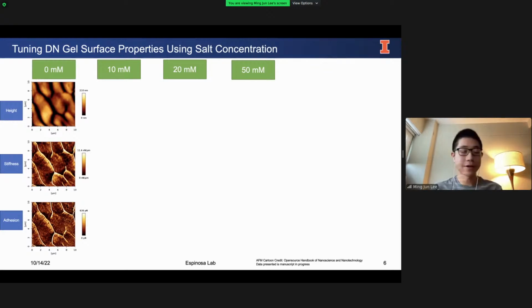I'd like to direct your attention to the first diagram on the top, the upper left. And we see a very unique microstructure for my double network hydrogel. It looks sort of like a grain structure, or even like the bubble wrap that we have in our shipping containers. The elevated orange grains, I believe, are the copolymer component, so that's the acrylamide-co-acrylic acid component, whereas the black areas that are lower in height, the valleys, I believe are the agarose network. And one reason why I believe this structure appears is that if you look at the second image, in the stiffness channel, the valley regions correspond to a higher level of stiffness. Through common knowledge in the hydrogel space, we know that agarose is the more brittle and stiffer network compared to the copolymer. So this is why I believe there are heterogeneities in the surface structure. The elevated sides are the copolymer, whereas the lower height is the agarose network.